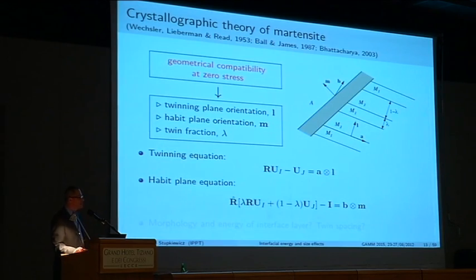Okay, so this is just an illustration of the very classical piece of theory which allows us to explain the formation of this austenite twinned martensite interface. This is the so-called crystallographic theory of martensite. This is the name which is used in the mathematical and mechanical community. The crystallographers call it phenomenological theory. Essentially, you start from the energetic considerations, but at the end, you just solve some geometrical compatibility conditions. So this corresponds to formation of the microstructure at zero stress.